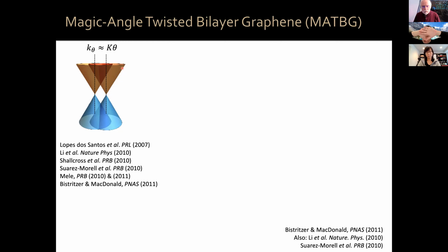Because we have rotated by a small angle, those 2 Dirac cones in reciprocal space also separate by a small distance in momentum space, which is proportional to the angle for small angles, okay? Now, this was studied by many people. And this is the electronic structure that would be realized if the electrons in one layer did not know that the other graphene layer exists.